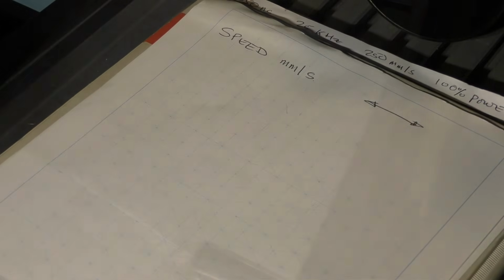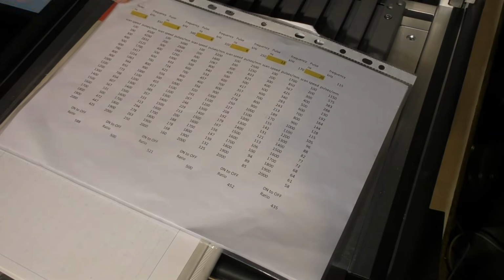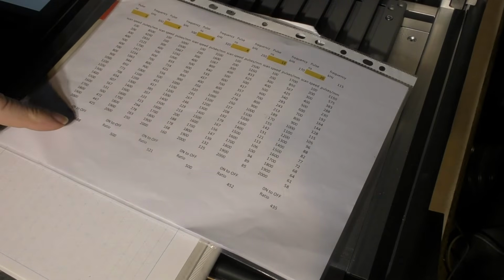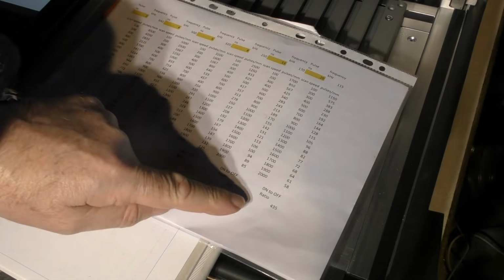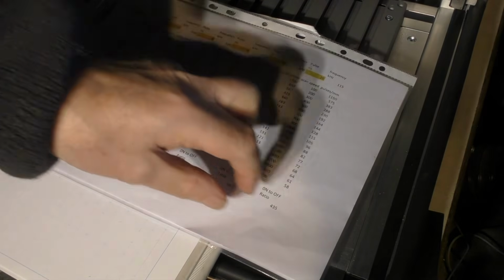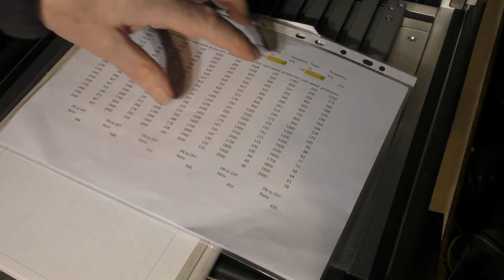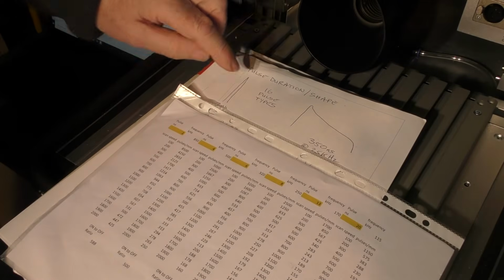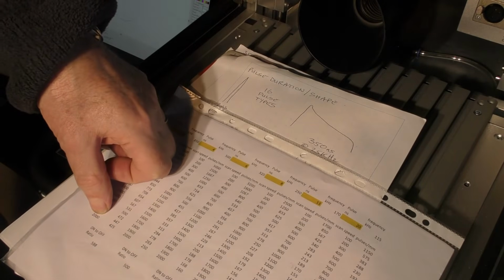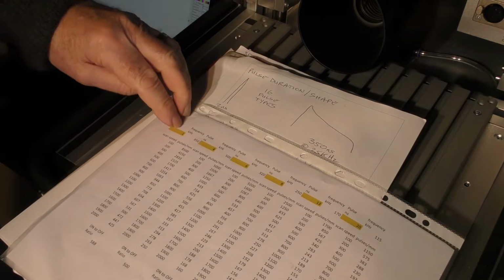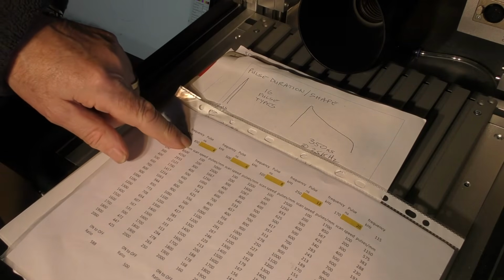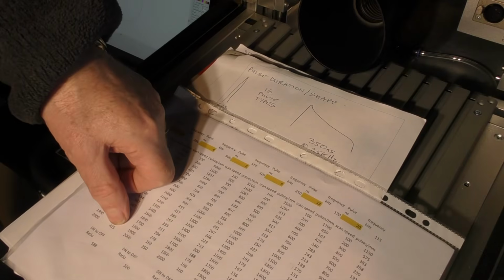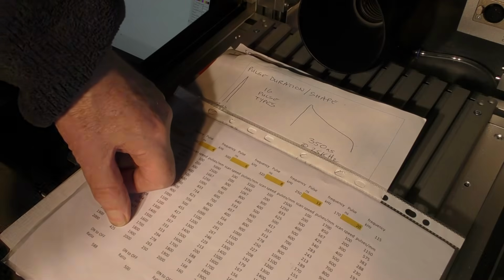Now we come back to speed. So when we look at my chart of the various frequencies and pulse lengths, you'll find that across the bottom here we've got a ratio which is 588, 500, 500, 435. They're all in the 400 to 600 to 1 ratio. Okay, so we've got a very long cooling period for a very short heating period, regardless of the pulse. So with our 2 nanosecond pulse at 2000 millimeters a second, even though we're running at 850 kilohertz, which is nearly 1,000,000 times a second, we're only putting down 425 pulses per millimeter.